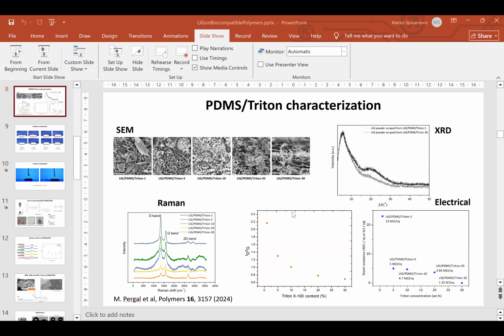It depends. If the question means monolayer on large scale, I think this is not possible. If within this porous structure you may have isolated graphene, yes, this is possible. Because graphene layers exfoliate also during the rapid thermal outgassing of the polymer. And the second part, yes, I mean, we're using Nd:YAG, many people using Nd:YAG lasers at 1064 nanometers. As I mentioned before, the absorption is only 15% for the Kapton. But yeah, you can do it also with this type of laser. You can prepare graphene with Nd:YAG laser.